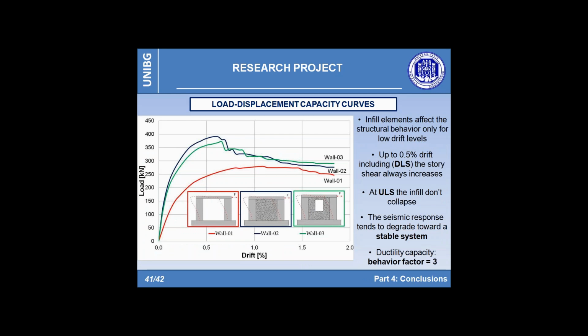The experimental results have shown that the presence of an infill element affects the structural behavior only for low drift levels. With the increase of the imposed displacement, the hysteretic behavior tends to degrade toward a stable scheme made only of shear walls, and thus not vulnerable to brittle collapse such as soft story, and capable of exhibiting ductility levels compatible with those suggested by the current seismic codes. In fact, a behavior factor equal to 3 can be assumed in accordance with the guidelines provided by the Italian code for structures with unpaired shear walls.